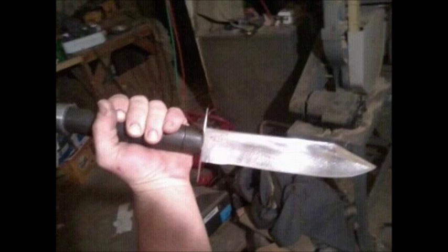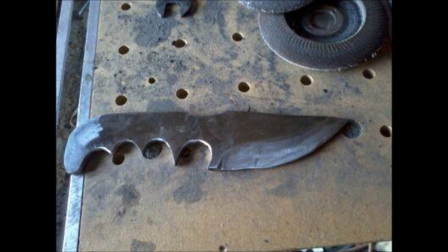Now, if your blade warps, there's three things you can do. You can either do the risky route: after you quench a knife, you plunge it in real fast, you give it like a second, and you pull it back out. And you have about a 10 to 12 second time gap where, if there's a bend or a warp, you can run over to the anvil and lightly hammer it back into shape. But that is such a risky thing. I've done it successfully once or twice, but I've also broken a few blades that way. So unless you really know what you're doing, I wouldn't suggest that.